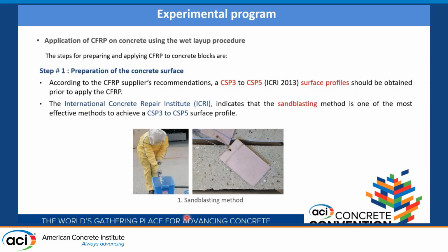For the application of the CFRP on the concrete, the wet layup procedure was used. The first step is the preparation of the concrete surface, a very important step. According to the CFRP suppliers' recommendations, CSP3 to CSP5 surface profiles should be obtained prior to applying the CFRP. The International Concrete Repair Institute indicates that the sandblasting method is one of the most effective methods to achieve a CSP3 to CSP5 surface profile.